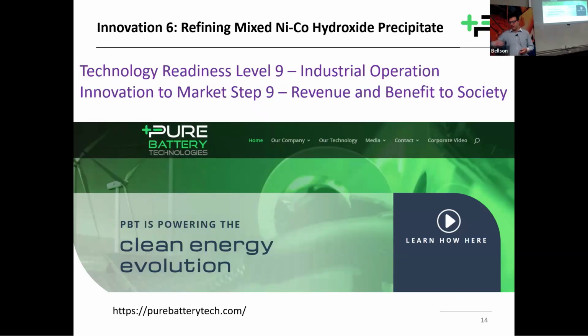And then you have this solvent extraction separation, which comes with its own issues. So the innovation was to selectively leach the nickel and leave the cobalt, manganese and iron in the residue using strongly oxidizing conditions. That was licensed to Pure Battery Technologies, which is a UQ startup company, and the initial investor in that was a UQ Minerals Process Engineering alumni.